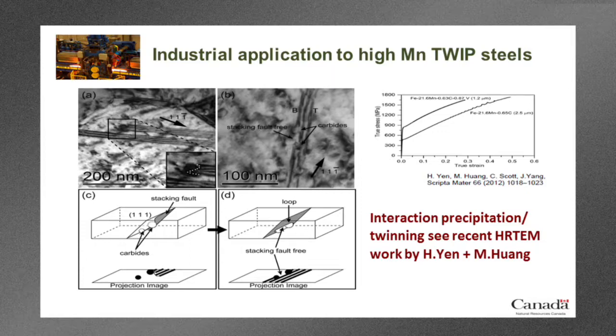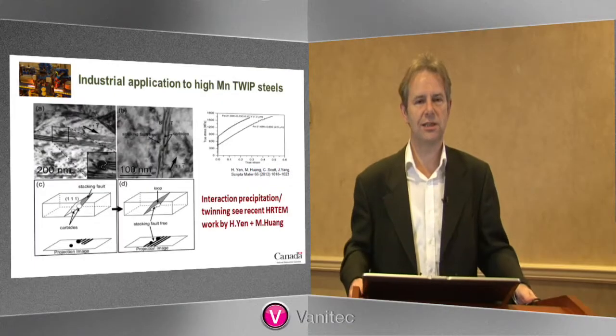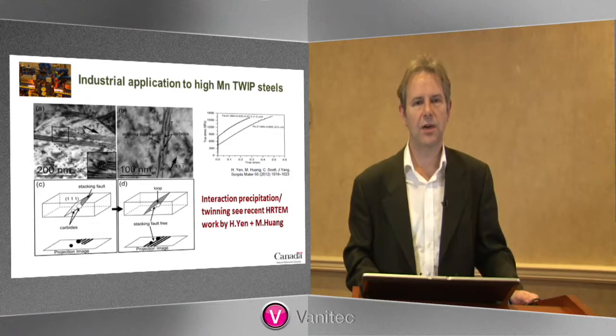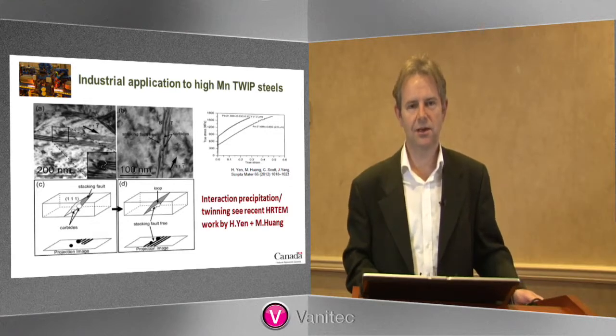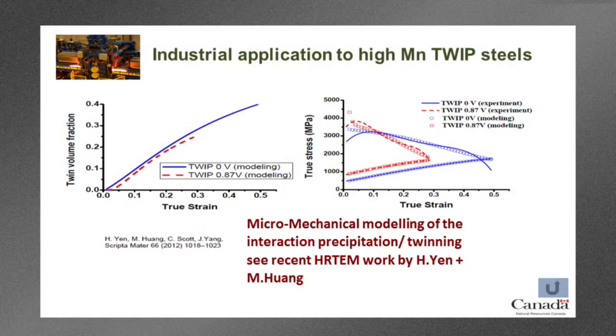I give the reference on this slide here, where they are looking in detail using very high resolution TEM experiments at how stacking faults interact with precipitates. And if you know how a stacking fault interacts with the precipitates, then that gives you a clue about the twins, because the nucleus of the twin is obviously a stacking fault. So again, I won't go into it in great detail because of time limitations, but I would encourage you to read the paper. They used that data to do some structure properties modeling.